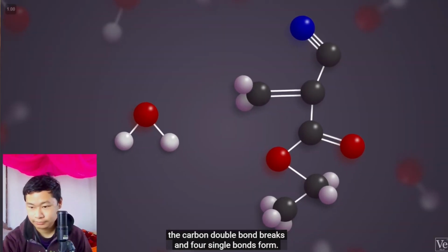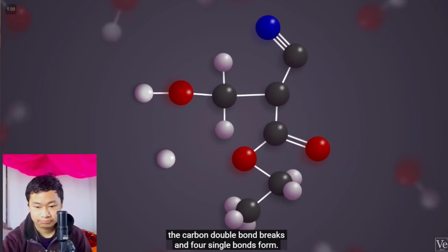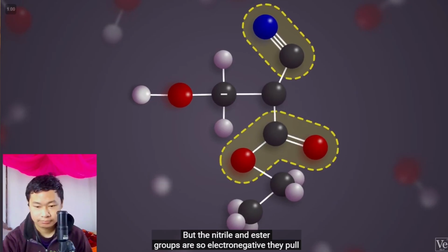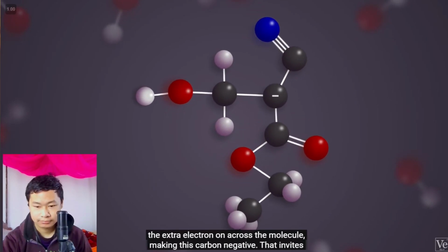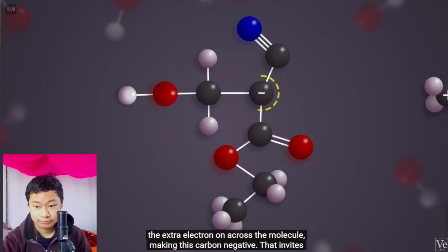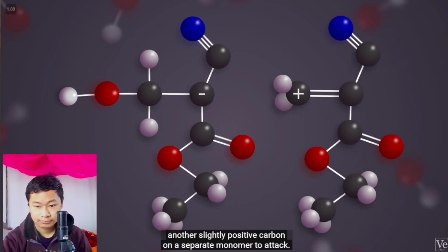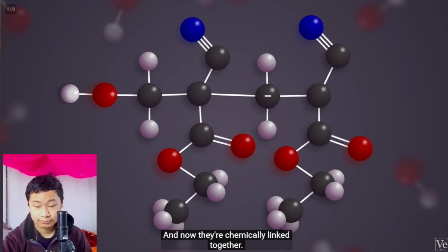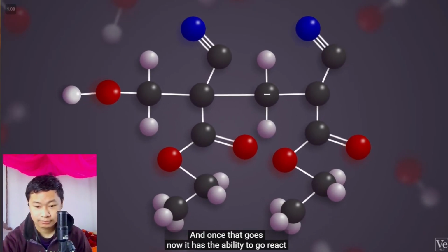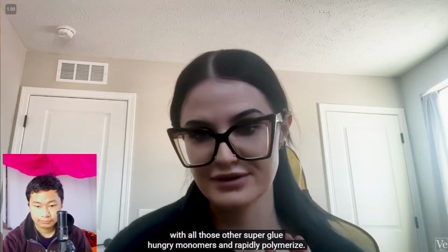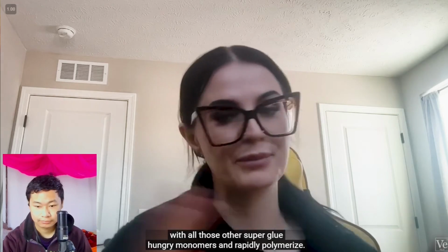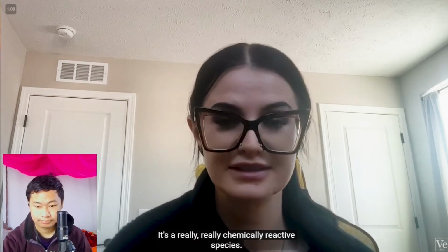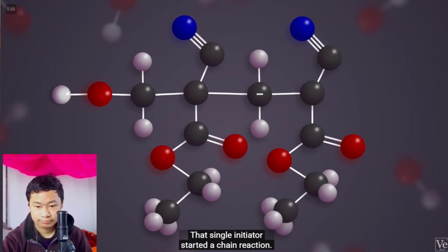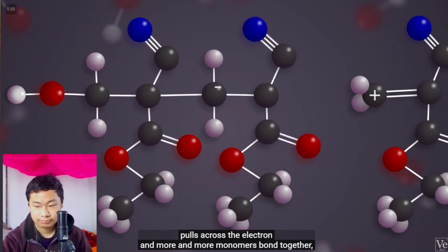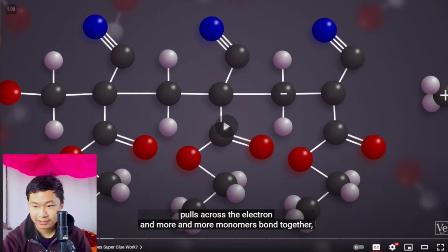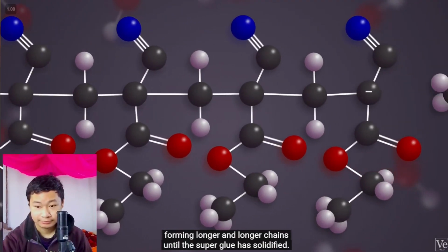In the presence of a negative ion, the carbon double bond breaks and four single bonds form. But the nitrile and ester groups are so electronegative, they pull the extra electron across the molecule, making this carbon negative. That invites another slightly positive carbon on a separate monomer to attack. And now they're chemically linked together, the start of a polymer chain. And once that goes, now it has the ability to go react with all those other superglue hungry monomers and rapidly polymerize. It's a really, really chemically reactive species. That single initiator started a chain reaction. The next monomer again pulls across the electron, and it just starts over and over again. More monomers bond together, forming longer and longer chains until the superglue has solidified.